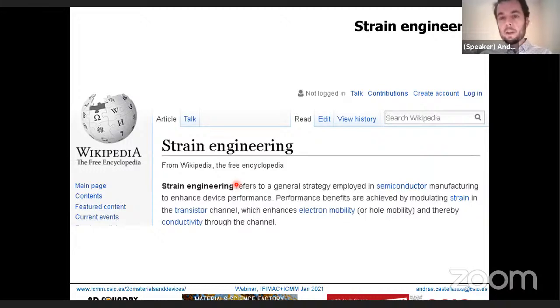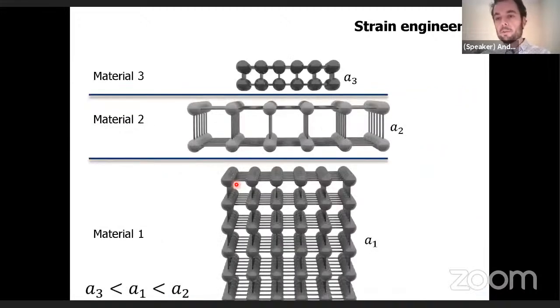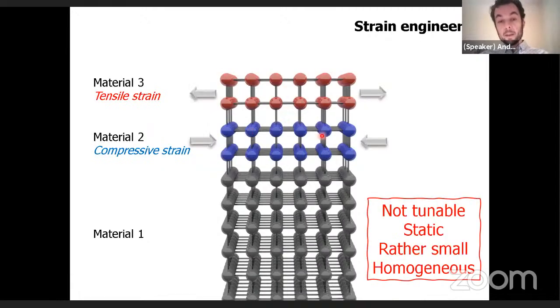The classical way of applying mechanical deformation in semiconductor industry and material science is by forcing epitaxial growth of materials with different lattice parameters. In this example, I've shown you a material with a given lattice parameter, and we force epitaxial growth of this material and this material on top—one with a smaller lattice parameter, one with a larger lattice parameter. When we force epitaxial growth of all these materials on top of each other, we apply a compressive strain to material 2 and a tensile strain to material 3.